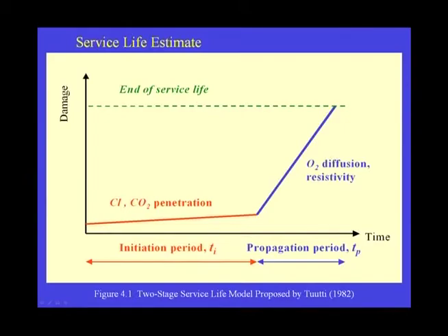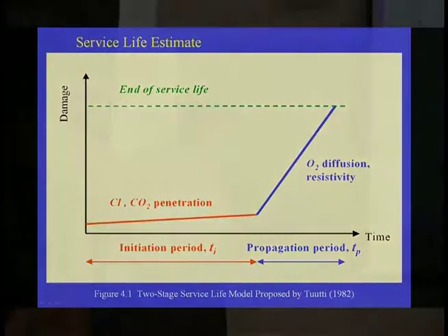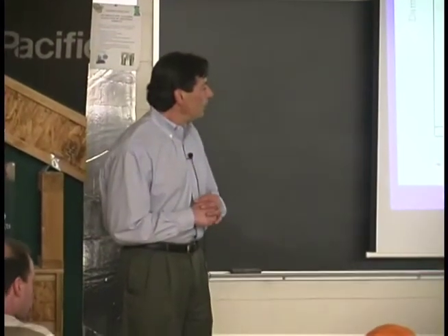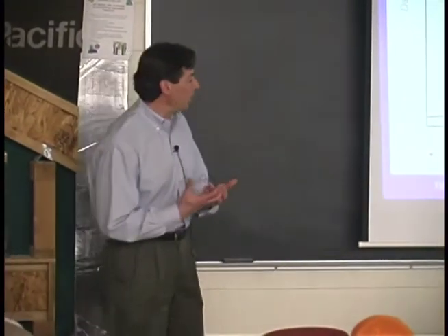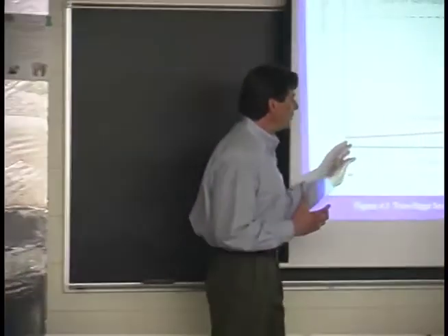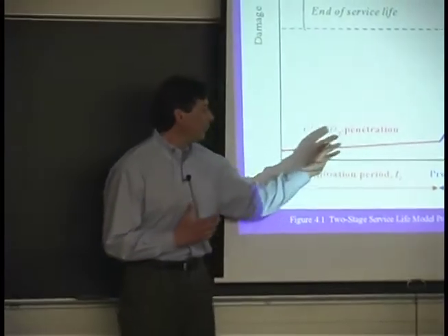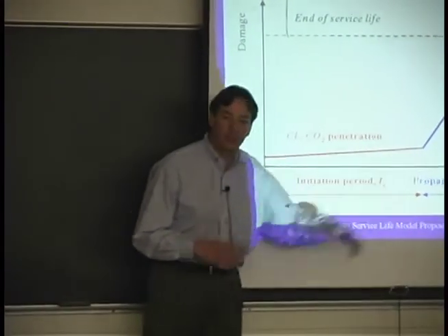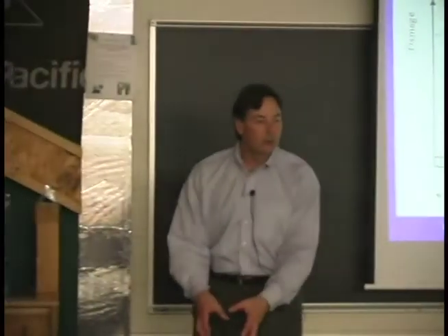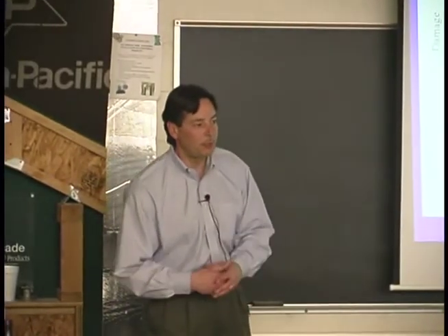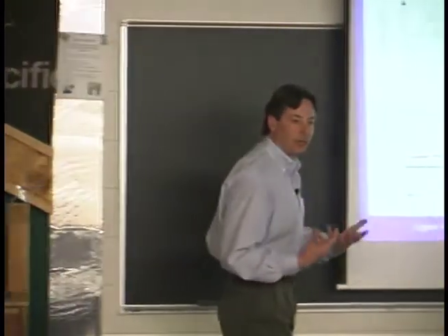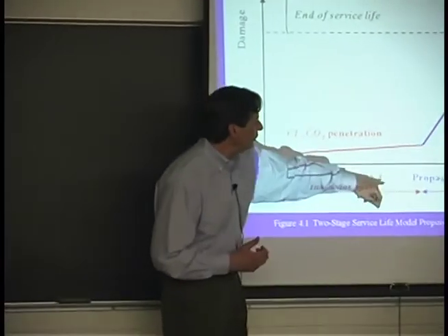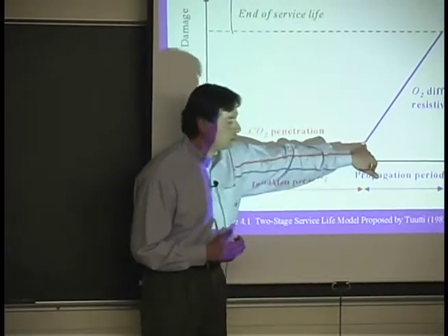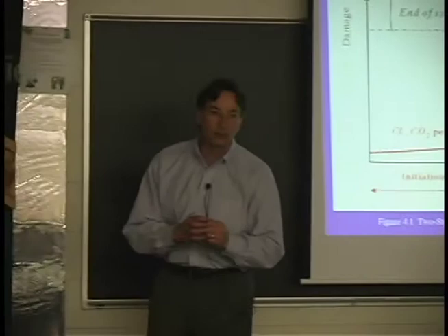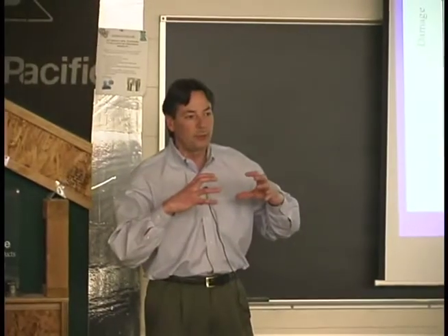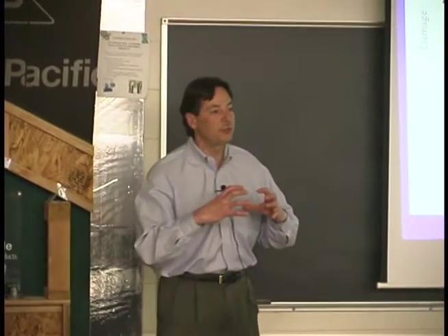This is a famous way of depicting it from Professor Tuutti back in '82. Concrete acts as a sponge. That's this initiation period here, where it's allowing chlorides and carbonation to actually penetrate and get into the concrete. There's no corrosion happening at that point in time. It takes a certain amount of electrolyte in the concrete to start corrosion. That's where we see the corrosion starts here, and then as steel corrodes, it effervesces and swells. It swells to 4 times its normal size.